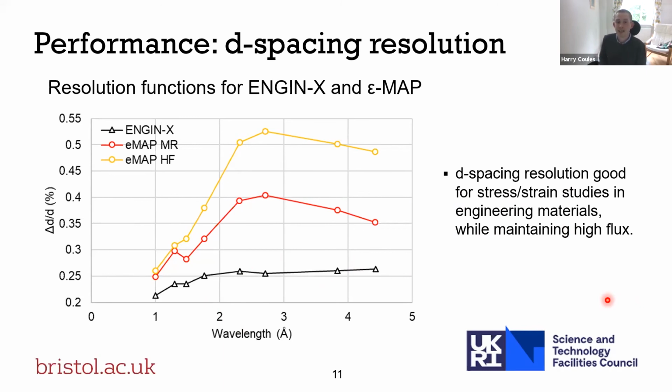Are the stresses inside it low enough? Can we use this thing? Diffraction resolution is important for making that decision, but in many cases you don't really need the very high resolutions that are available on ENGIN-X. On ENGIN-X, you're taking a big hit in terms of counting time to enable that, which actually limits the types of studies that can be performed with it. So that's the philosophy behind this proposal for EMAP.